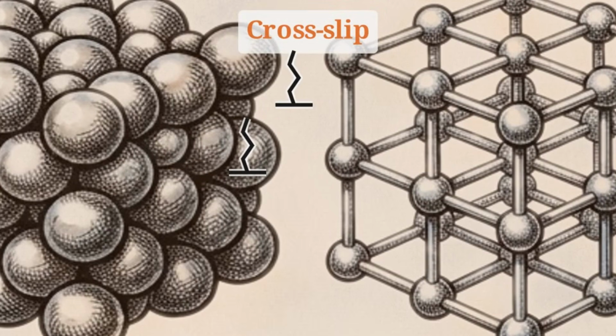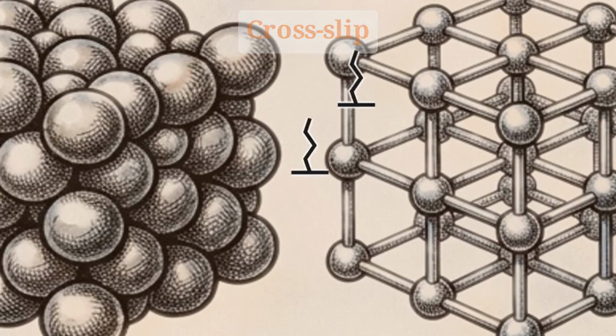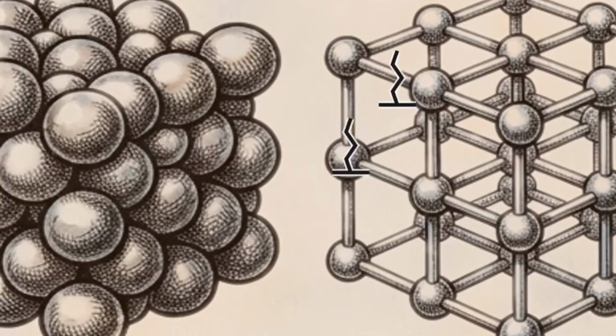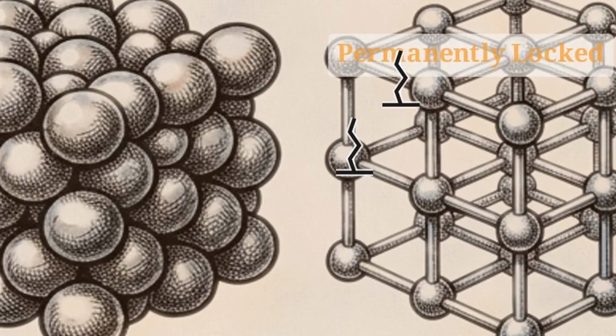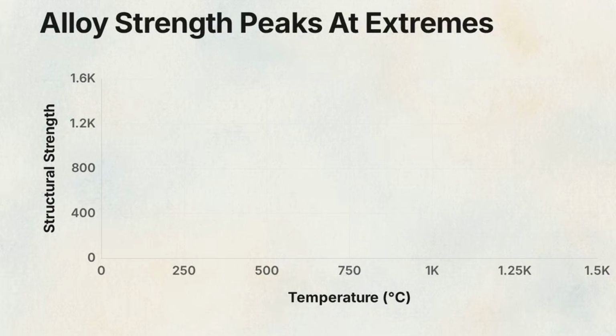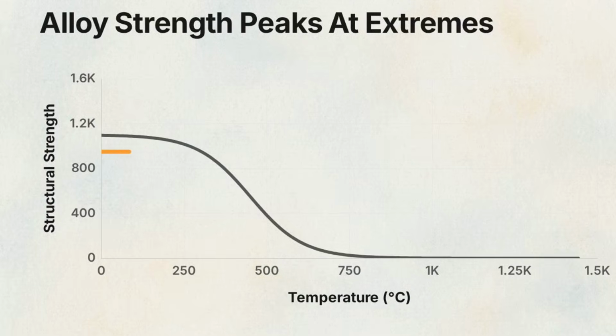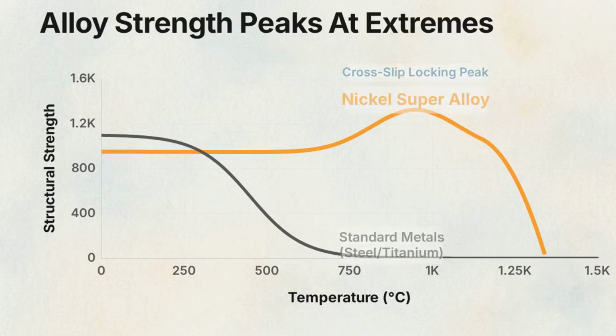As the temperature rises, the extra thermal energy causes these dislocations to jump to a different atomic plane, a process called cross-slip. Once the dislocations are separated like this, they can no longer travel together through the lattice, locking them permanently into place. Because of this specific atomic maneuvering, the superalloy doesn't soften as it gets hot. Instead, its strength actually peaks right at the extreme temperatures, where other metals would simply give way.